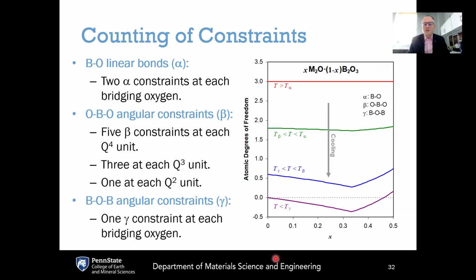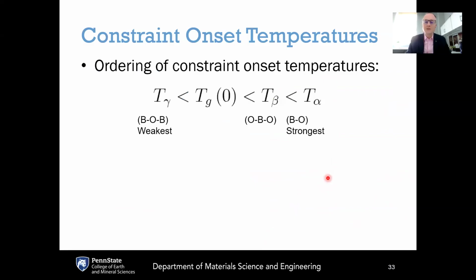So this graph is really interesting because it shows us the composition dependence in terms of X, and it shows us the temperature dependence as we cool the system from high temperatures down to lower temperatures. As that cooling takes place, we are losing atomic degrees of freedom as we get more and more rigid constraints in the system upon cooling. Now, the glass transition temperature has to occur where we've got some rigid constraints in the system, but it's not yet fully rigid. And so mathematically, we can determine that the glass transition temperature must fall between the T gamma and the T beta.